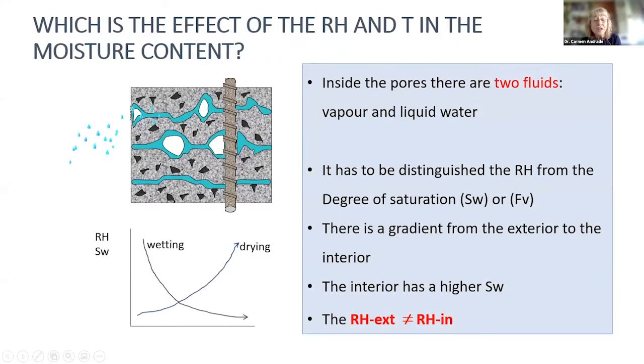And in the case of the concrete, when we wet it due to the raining, we have a gradient from the exterior to the interior. That means when it is raining, it takes 2 or 3 days, in our case with a 3 centimeter cover, or even longer, for this external water to reach the bar by capillarity. If it is raining and you measure the corrosion rate immediately, the bar is not noticing anything. You need a longer time for the liquid water to reach the bar by capillarity.